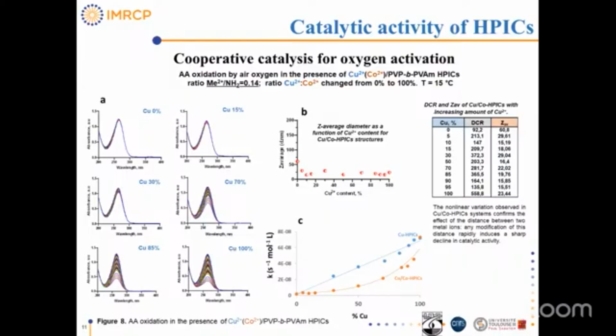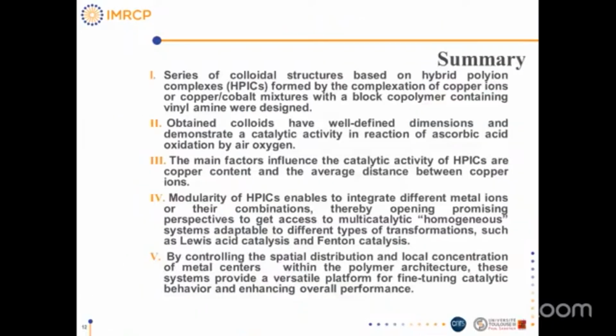As shown in figure 8c, in general, activity in copper-cobalt HPIC systems is systematically lower than that in copper HPIC system with the same copper concentration. The nonlinear variation observed in copper-cobalt HPIC systems confirms the effect of the distance between two metal ions. Any modification of this distance rapidly induces a sharp decline in catalytic activity. And next picture, please, with conclusion.